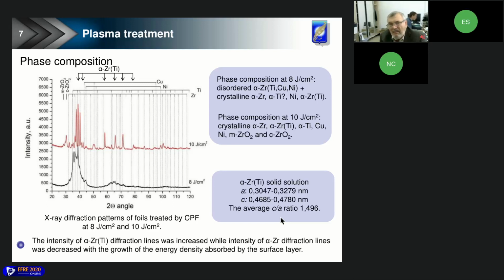Zirconium oxide with monoclinic crystalline lattice is a stable polymorphic modification of zirconium, so it's the low temperature phase. Presence of high temperature zirconium oxide with cubic lattice could be connected with its stabilization by other alloying elements.